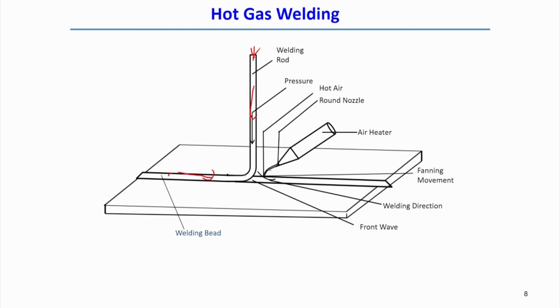welding bead. To soften this welding rod, we can use an air heater, and through a round nozzle the hot air passes to the interface. Simply by application of the hot gas stream, it tries to soften the material, and then there is a continuous movement along the welding direction, and it creates the weld joint between the two components. So, this is the technique for hot gas welding of plastic components.